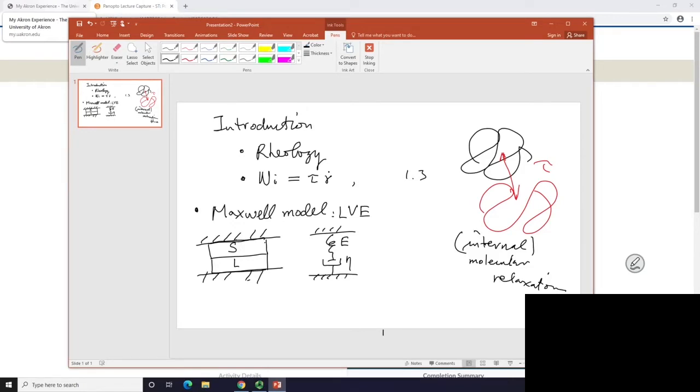When you try to examine such an abstract construct, obviously your polymer is not that. I failed to take a piece of my favorite material, PDMS, which is an uncross-linked melt. It has a Tg of minus 100 C, so at room temperature it's a liquid, and that piece of melt is just like a silly putty.